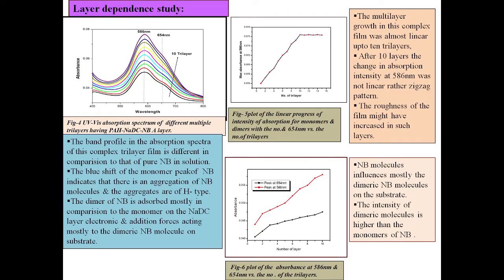Now we discuss the layer dependency. The band profile in the absorption spectrum of this complex trilayer film is different in comparison to that of pure NB in solution. The blue shift in the monomer peak of NB indicates that there is an aggregation of NB molecules and the aggregates are of H type. The dimer of NB is adsorbed mostly in comparison to the monomer on the NaDC layer, electrostatic and additional forces acting mostly on the dimeric NB molecule on the substrate.